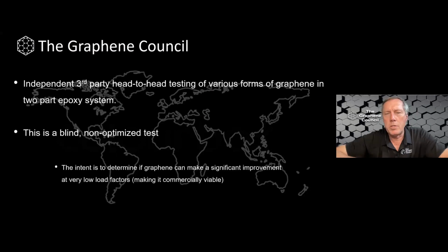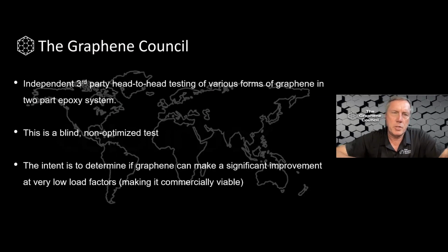So what is the role of the Graphene Council in this presentation and for this particular project? We recognize that the composite sector needs data about whether or not graphene actually works, and if so, how well does it work? And so we developed an independent, blinded, head-to-head comparison of more than 15 types of graphene material in a standardized 2-part epoxy system. And we used an extremely competent lab. We used the University of Maine with their Advanced Composite Center to do the physical testing. And we worked together with Vibrance with their expertise on doing the master batches of the material, which you'll hear more about in just a second. Next slide.